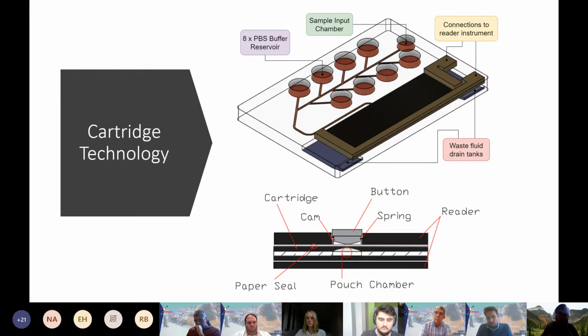So we apply heat treatment at 95 degrees for 10 minutes, which basically denatures the aptamers, releasing the previous sample's HA back into the solution. Then we wash with urea solution to remove that unbound HA from the previous sample. And then we reform the aptamer by leaving it at room temperature for 15 minutes. So that's our recycling process. And aspects of this have been tried by other people in research, but we've put it all together.